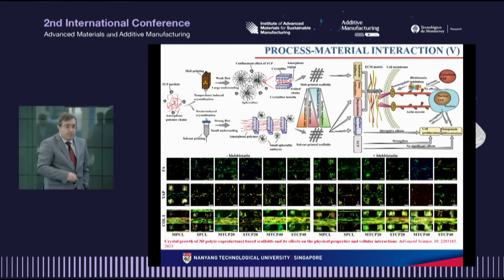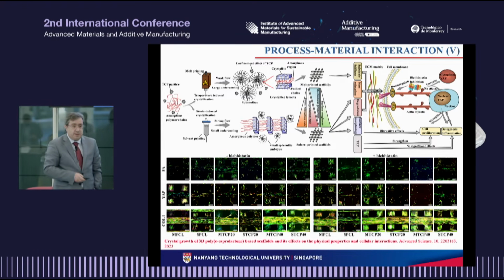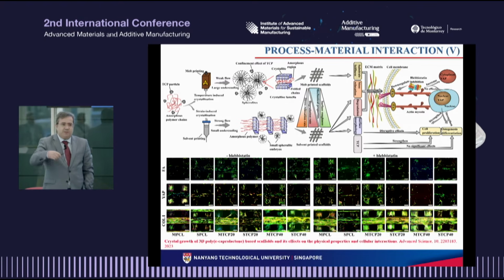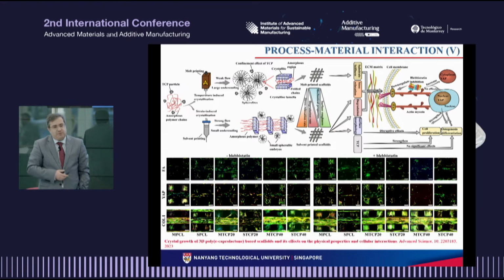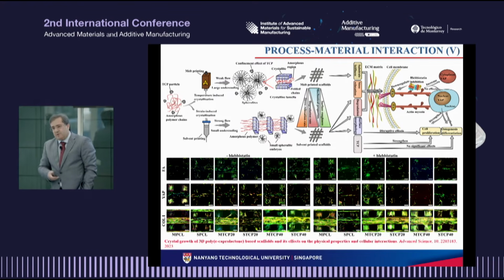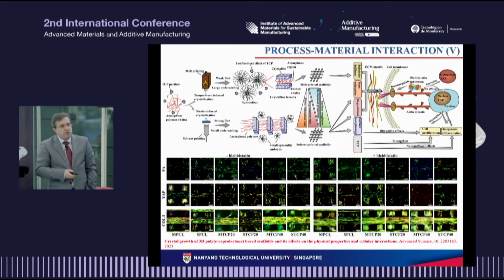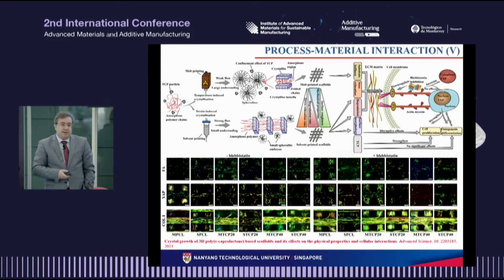The scaffolds that we produced through the melt printing route show high mechanical properties. Printed filaments were quite stiff, and when we seeded the scaffolds with cells, we observed the formation of large levels of YAP promoting cell proliferation.